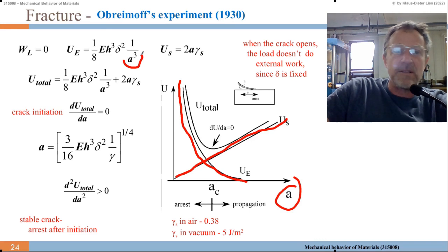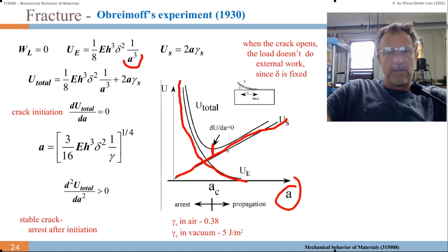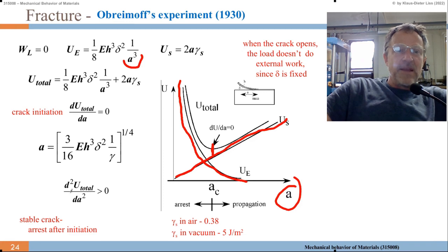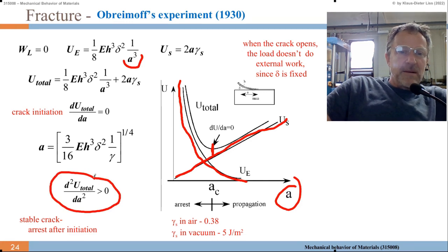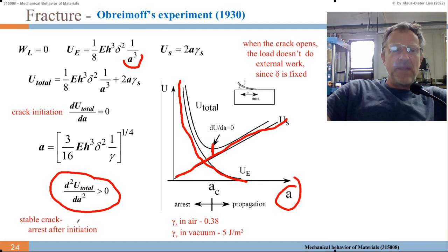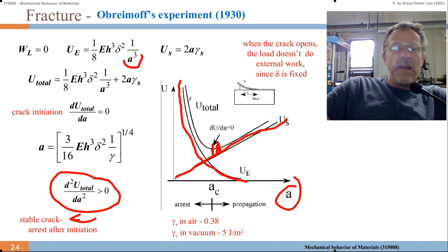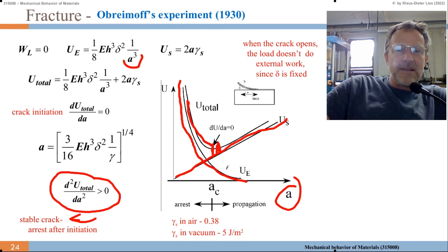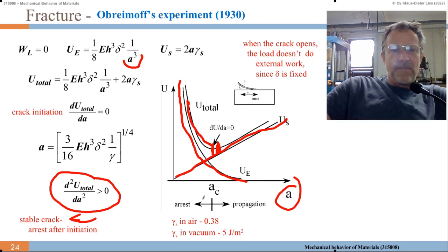That means, again, I get a minimum here, but this time I have a concave curvature - it's open to the top. That means d squared U over dA squared is larger than 0, and this is a stable condition. That means if I make my crack longer than AC, it would cost me energy, so it would not grow longer than AC. If I have an initial crack shorter than AC, then it opens and opens and opens until it reaches this critical length A.